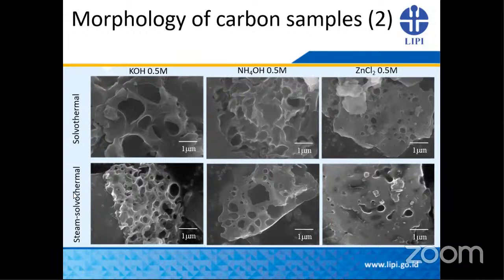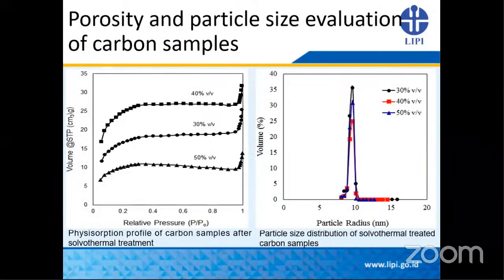So we can see here, if we use a steam solvothermal method, we can see here the pore development of the carbon sample, and also we can avoid the collapse of the pore structure of the carbon sample. We can see here, if we use steam, the pore structure is still better compared with the solvothermal method. And also we conduct the measurement of the nitrogen gas adsorption, and we can see here using the 40% volume of the solvent, we can get the highest gas adsorption profile.